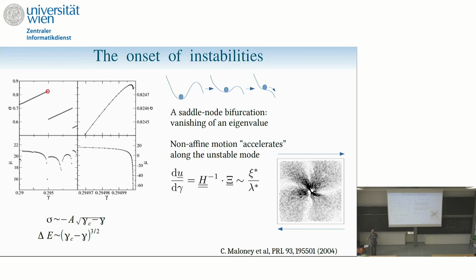Because you have a series of instabilities, you have to go through a series of soft modes. Each instability is a localized soft mode. So each instability is associated with the vanishing of the modulus in a small region. After you pass this instability, this region in general becomes meaningless. It's just like the others.